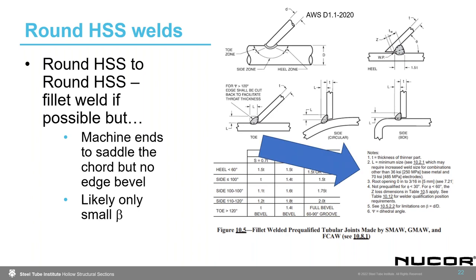There's also in D1.1 in this figure 10.5, there's this note 4 here that talks about if the angle is less than 60 degrees, then the Z-loss values in the table in D1.1 need to be applied for fillet welds, even though they typically only apply to PJP welds. So to keep the dihedral angle between 60 degrees and 120 degrees, there's a complex effect of the betas and the dihedral angles, which is just going to change continuously around the joint as you go. So it's complicated, but definitely needs to be considered. So it's not a slam dunk to assume that you can get a fillet weld here. There's a decent amount of work on the fabricator's part that needs to be done.